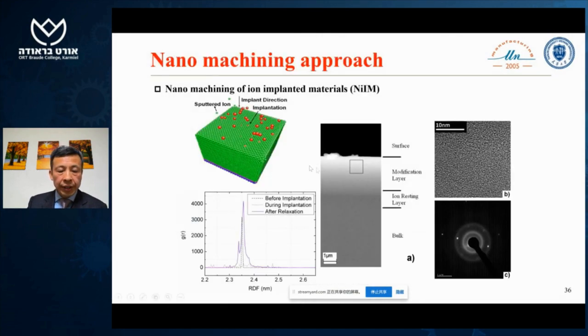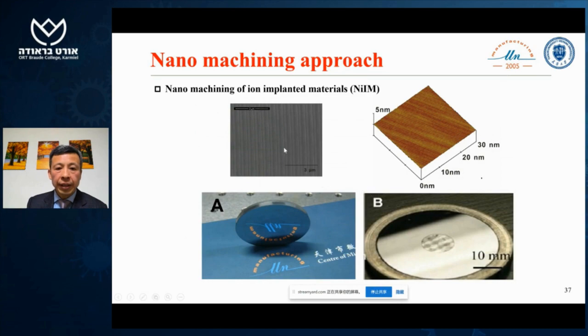And you can see here, we use the radial distribution function to analyze the modified layer. Then you can see this RDF figure is actually not single crystal anymore. And if we use TEM to further analyze the modified layer, we can see it's a kind of amorphous. That means the material property is changed from brittle to ductile. Then we can machine the brittle materials.